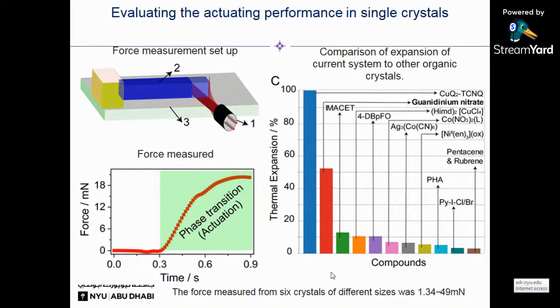And also in the literature, there are many compounds which show expansion and contraction. So far, our compound is the best. As you can see in the red bar, our compound is the best. But you can also see there is a 100% expansion showing compound, placed as a blue bar. But the interesting thing about this compound is that it is not reversible, and the transition is not reversible, and the crystals only show this kind of expansion by applying pressure. That means not by temperature variation. You have to apply the pressure, then it increases its length. It's a one-way reaction. So considering these drawbacks, we would like to say that our compound is the best so far.